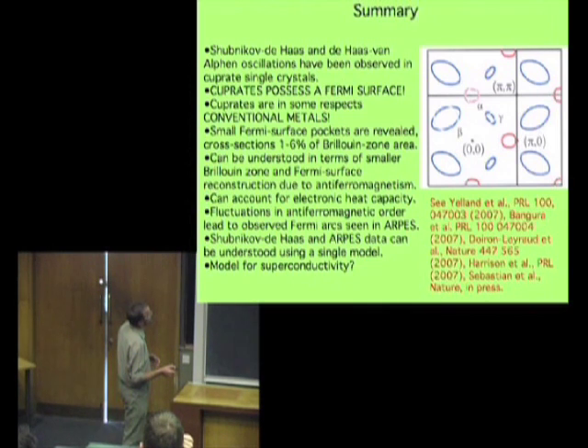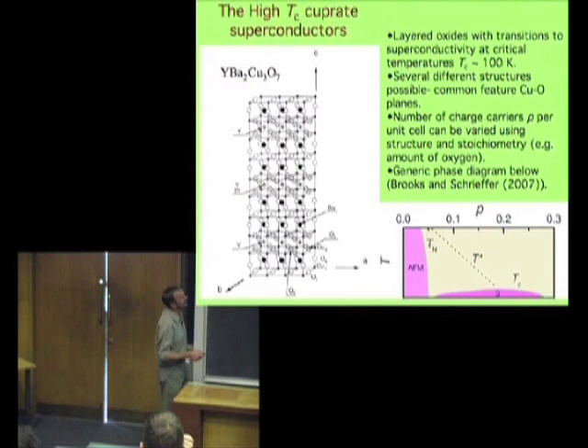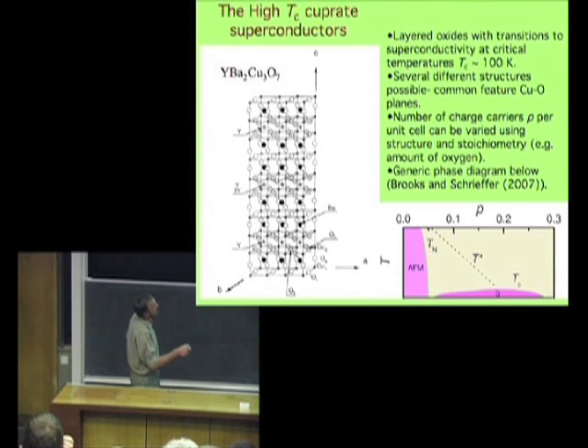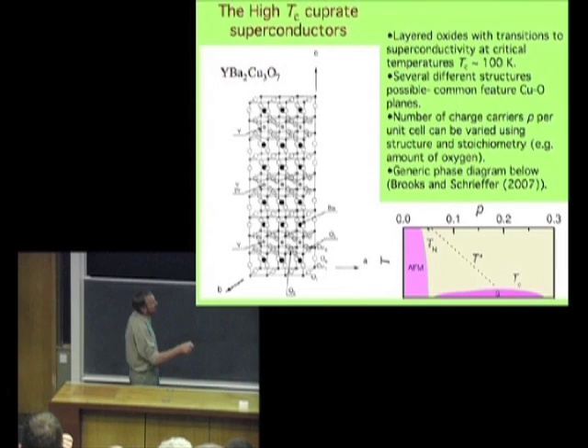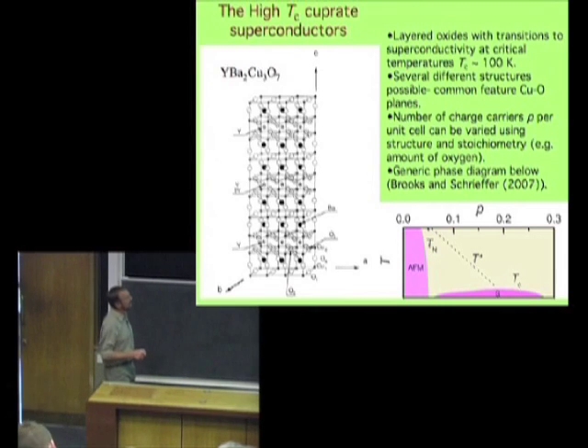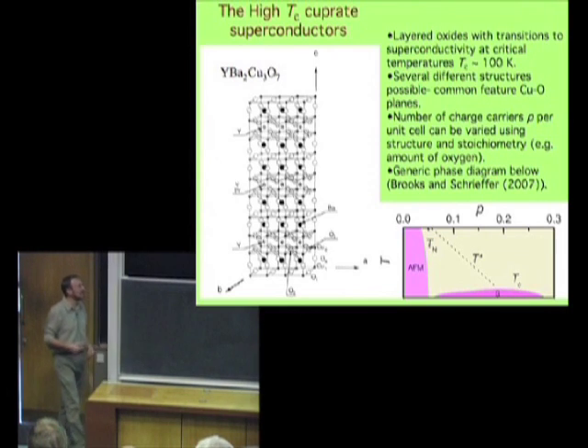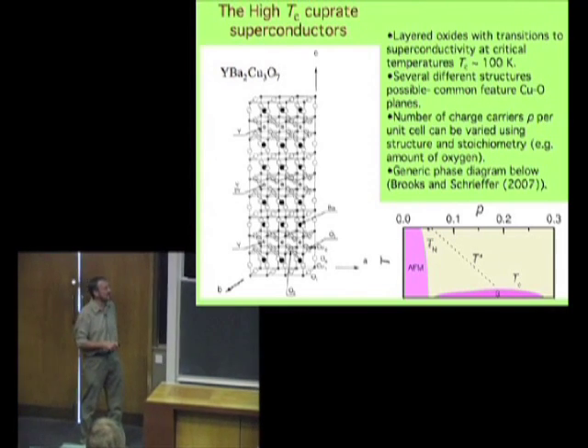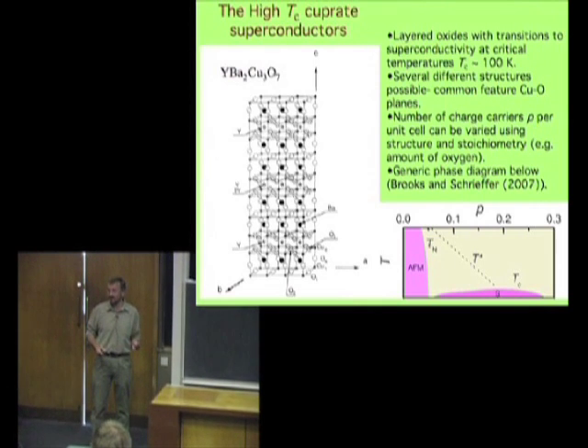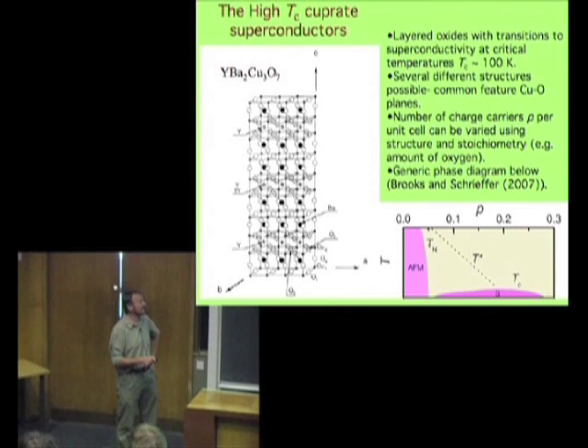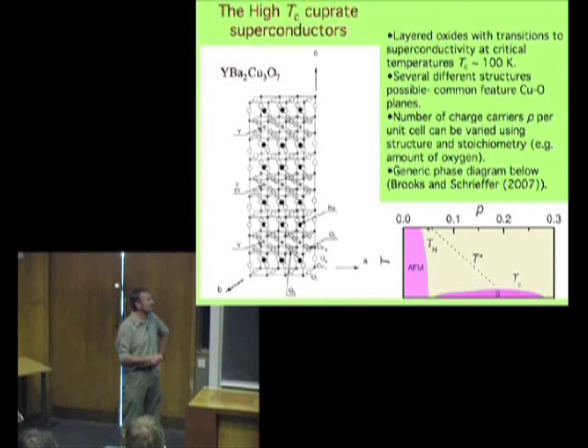I'm sorry, I should have gone into Slide Manager or whatever it's called. What he's talking about is that there's an idea that this T-star thing here is in some way separating a funny thing, a non-Fermi liquid, from a Fermi liquid up here. Now, if that were the case, you have to say, why is it that we see a smooth transition, without any histrionics or odd behavior, from superconductivity into the metallic state? Which gives us the quantum oscillations, and even why, in the case of the magnetic field measurements we did at Tallahassee, we see quantum oscillations of the same periodicity within the superconducting state.